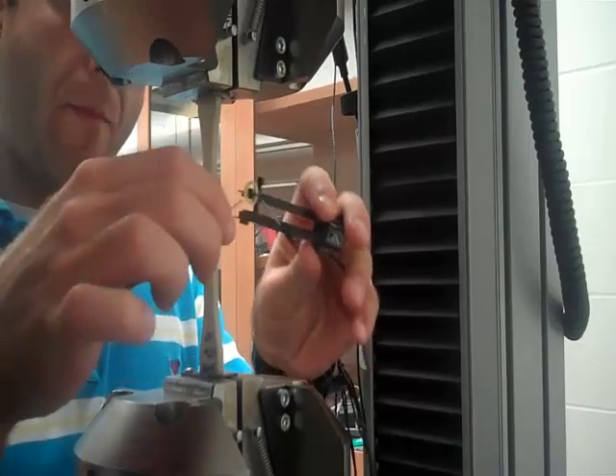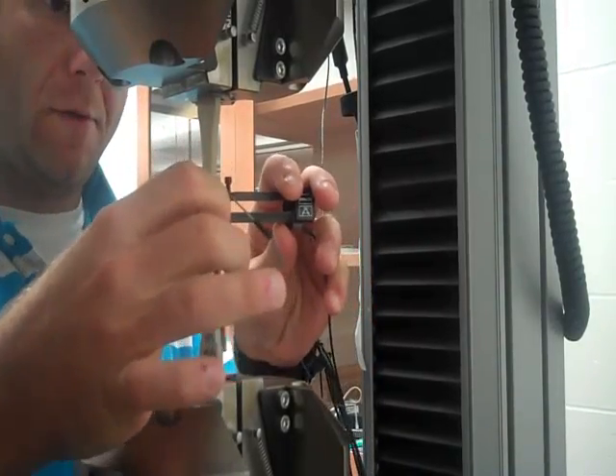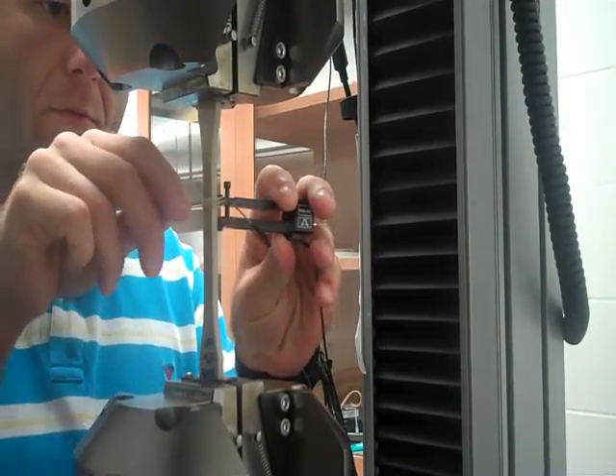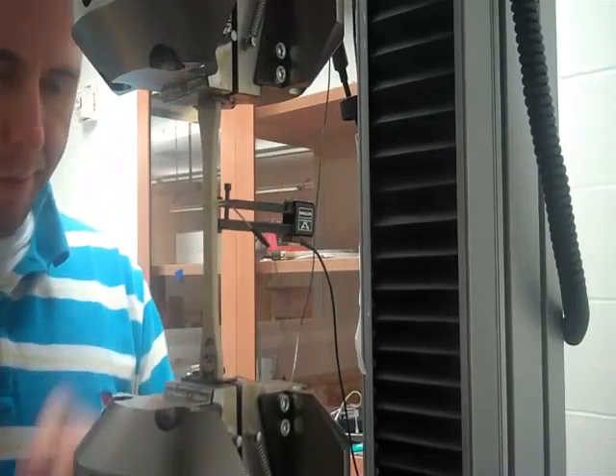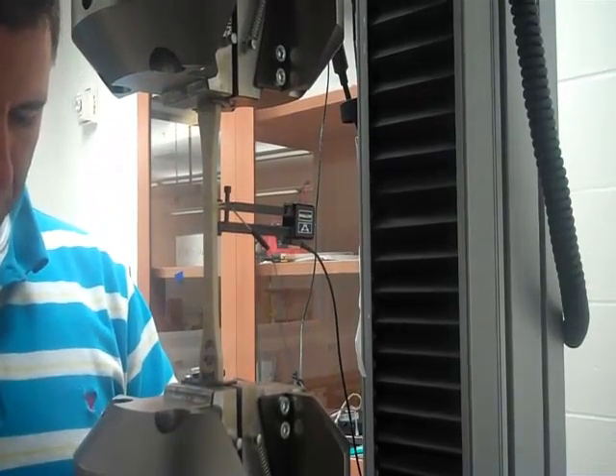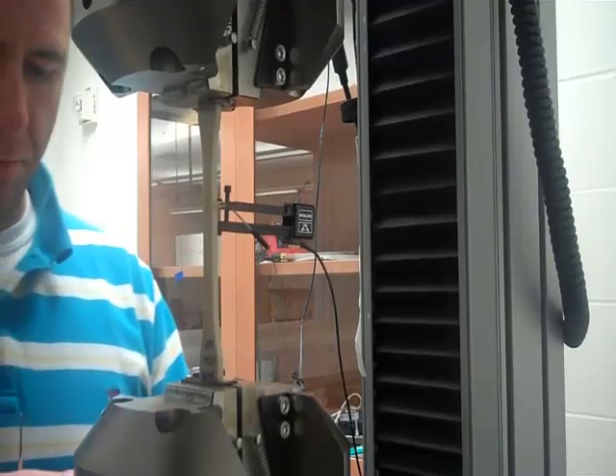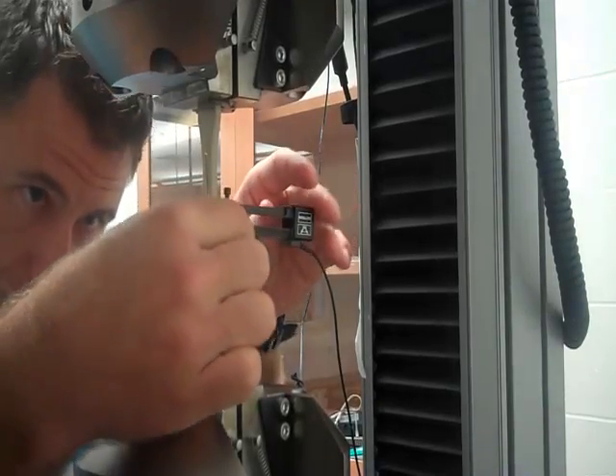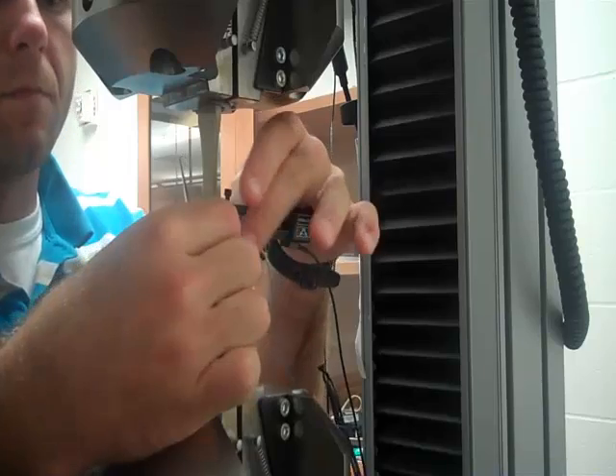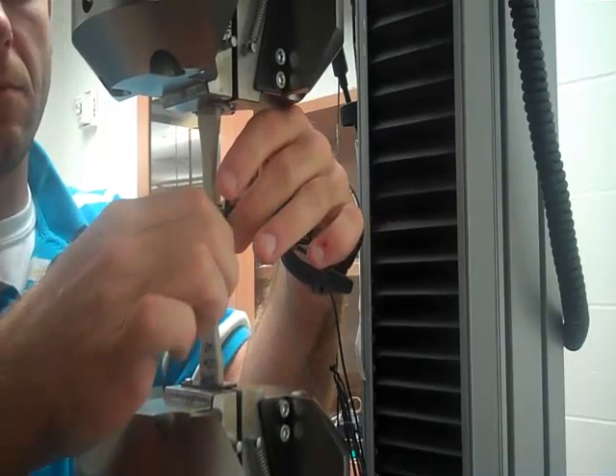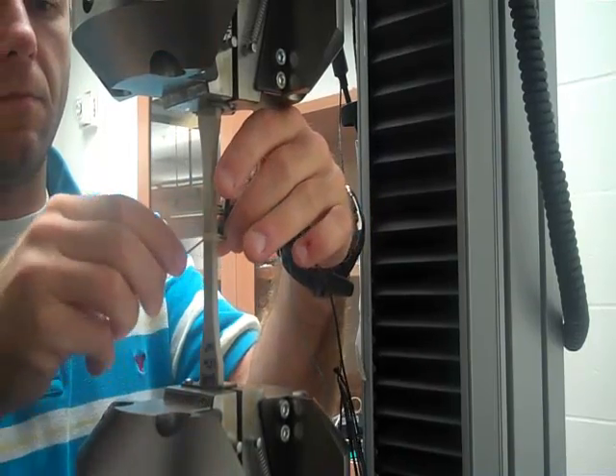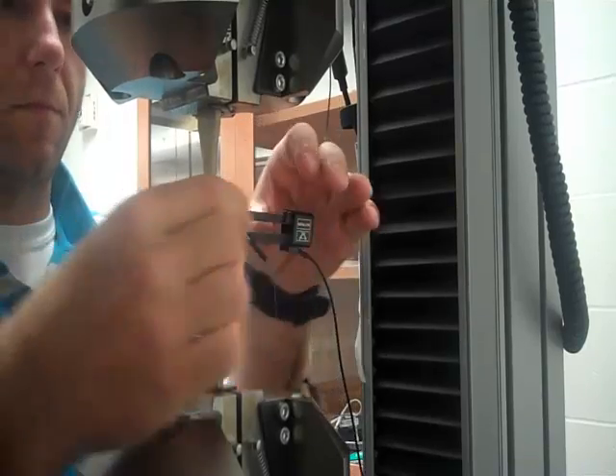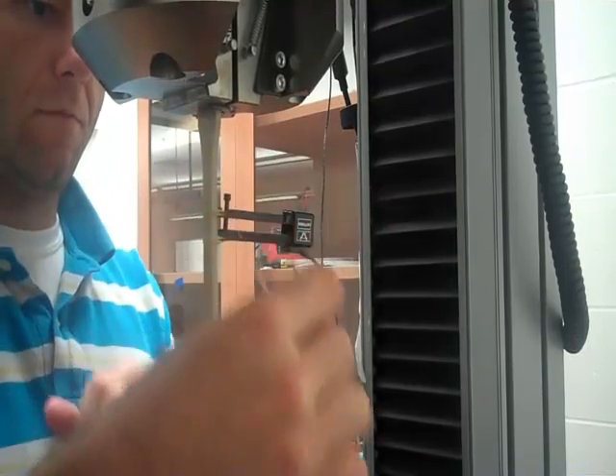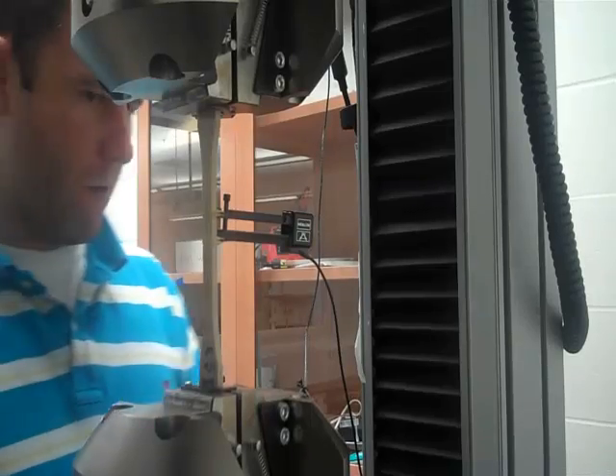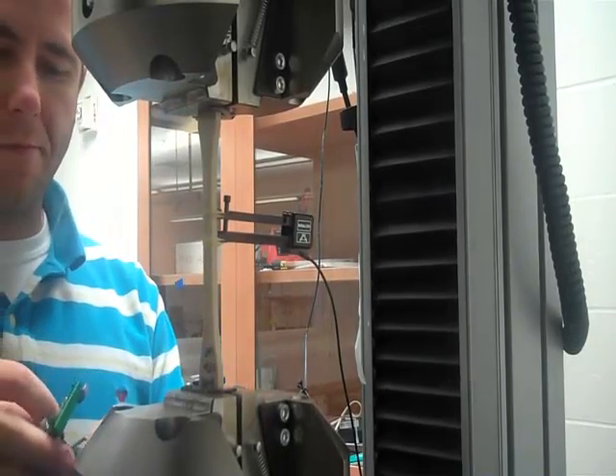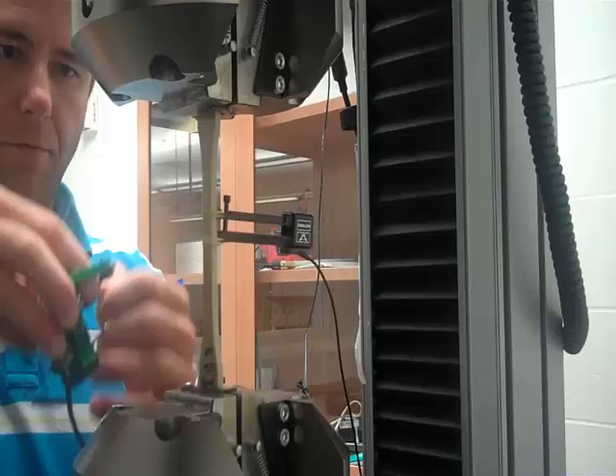With the sample experiencing 0 load, we can now place our extensometers onto the sample. The first extensometer is an axial extensometer and measures the axial strain the sample undergoes during the test. It's held on with rubber bands on the top and bottom legs, with each leg having a sharp blade that's touching the sample surface. Any extra adjustment of the extensometer when it's touching the sample can cause surface defects, which in turn can cause premature fracture. Once placed onto the sample, we can remove the safety pin and the extensometer is ready to measure.